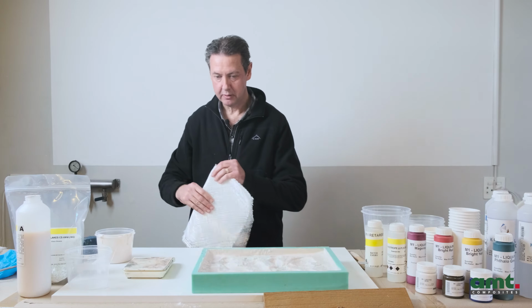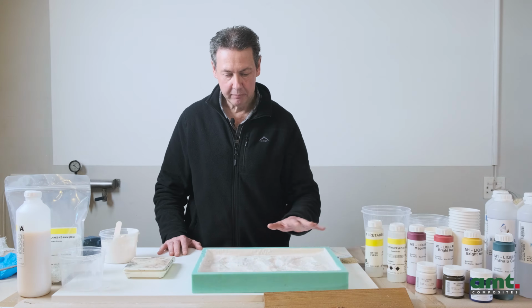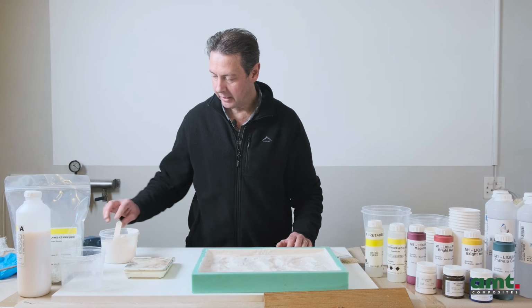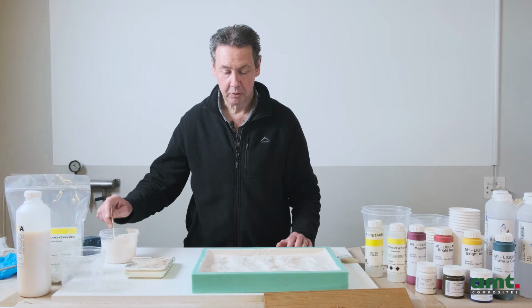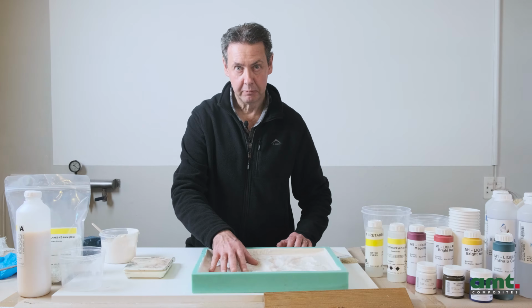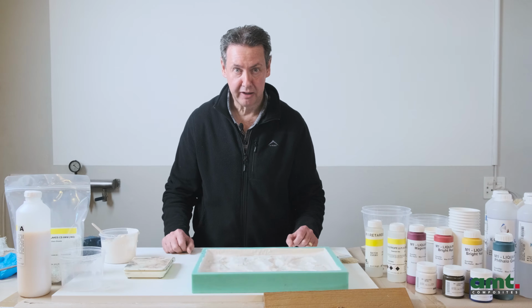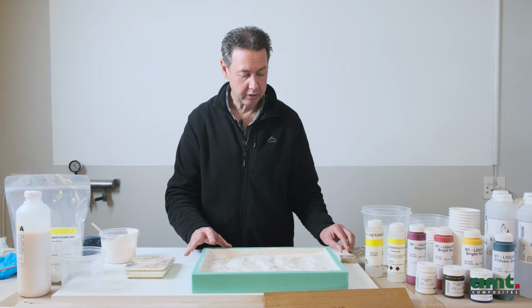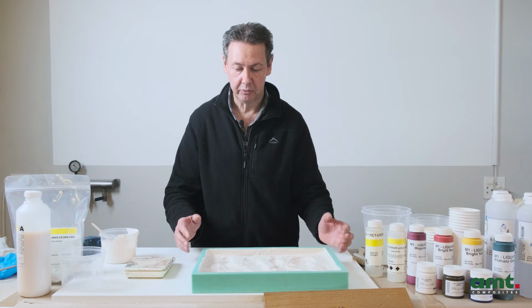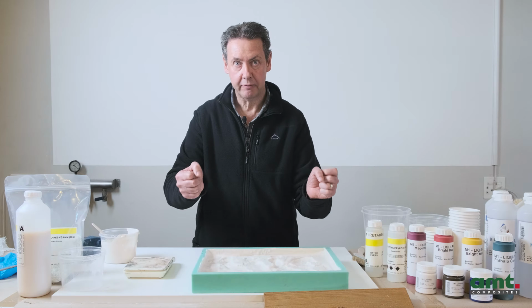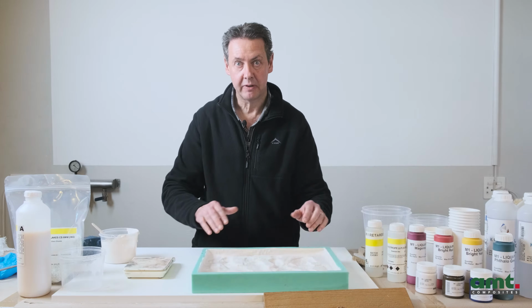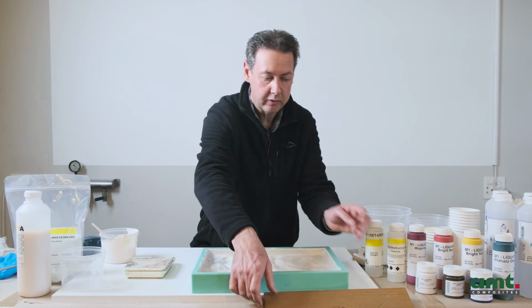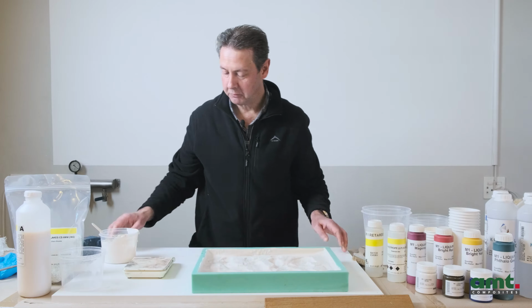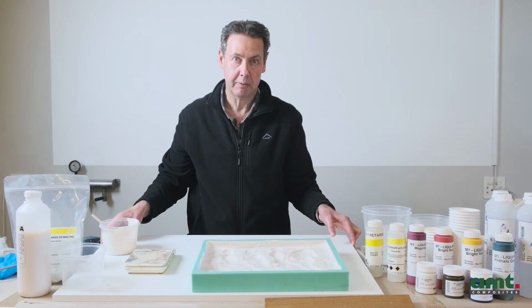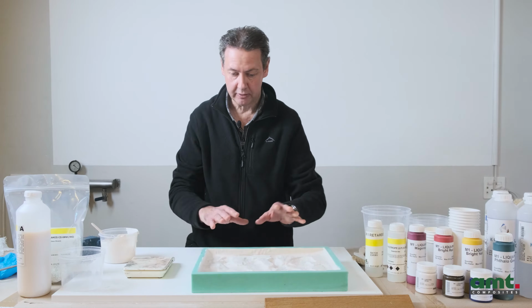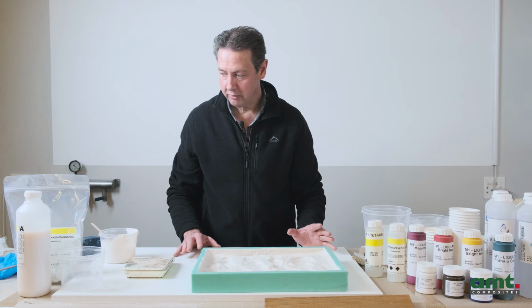Okay, so it's been about 30 minutes since we applied this face coat into the silicone mold, and this is what we mixed up, so it's become quite nice and hard. So this has become touch dry, which is now perfect for us to apply the reinforcement layer. At this stage, we don't want to pick up the silicone mold, because if we actually move the silicone mold, the mold's going to flex and it's actually going to break and crack up that gel coat. So an idea, if you are doing work with a silicone mold, is to have it on a board, because if you do need to move it, you can just pick up the board and move it around. So we're now ready to do the reinforcement.